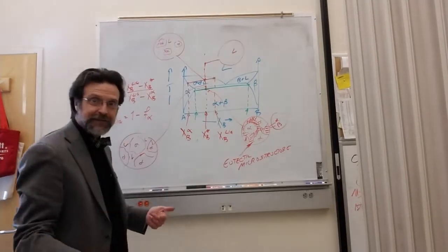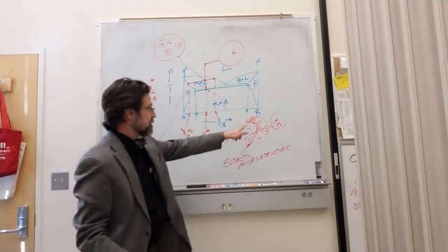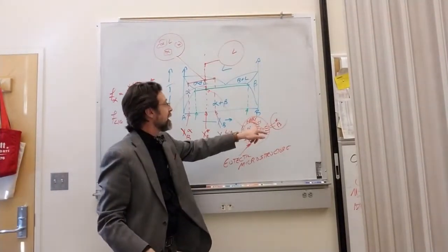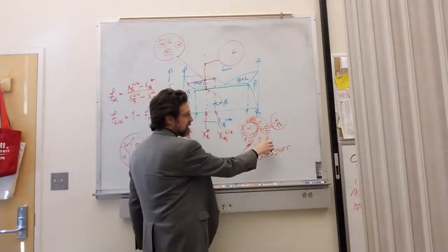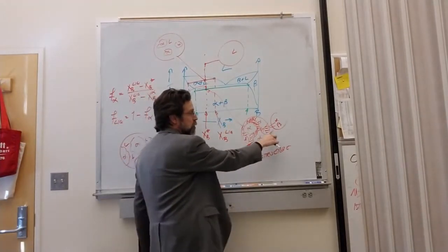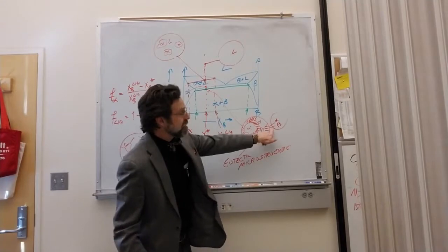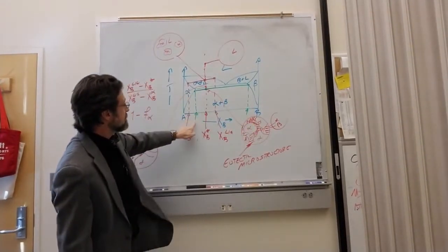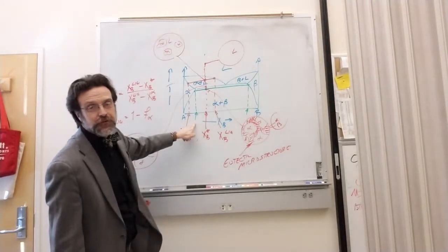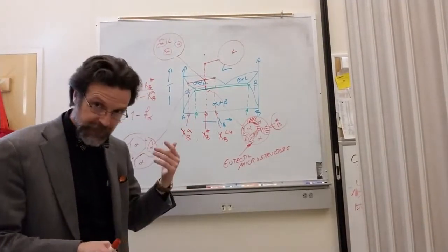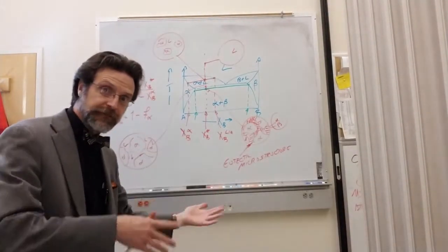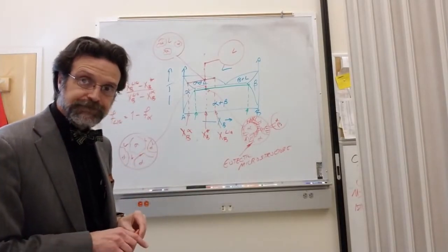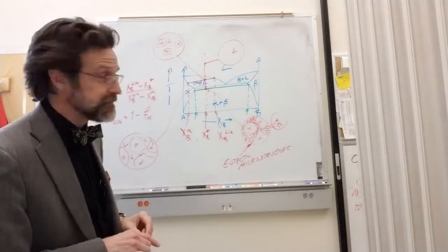What's happened is this beta is B atom rich, and we get a eutectic microstructure with alpha and beta. The beta is B rich, and the alpha is A rich. So we're getting a segregation of the A atoms and the B atoms into alpha and beta compositions, or the alpha and beta phases.